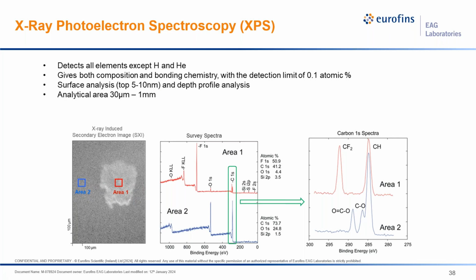And we can take survey spectra, the two spectra shown here from the two different regions on and off the contamination. But when we blow up and look at the high resolution, now we can see where the chemistry starts to come in, where we can see the carbon-carbon bonding and carbon-fluorine bonding, start to identify that these are some sort of Teflon fluorocarbon type of contamination on the surface. All of that can be nicely quantified. So we get composition, some bonding information, detection limits at or below 0.1 atomic percent. But we're a little bit limited by the analytical area in XPS. You can focus the X-ray beam down, say, about 30 microns at best.